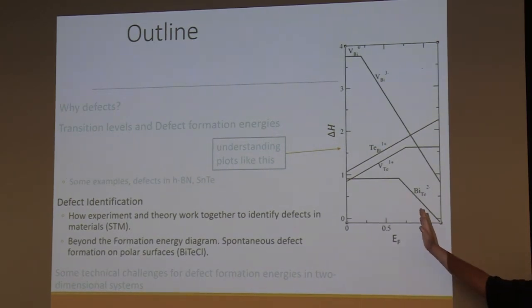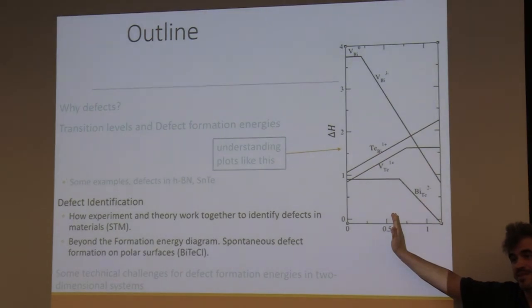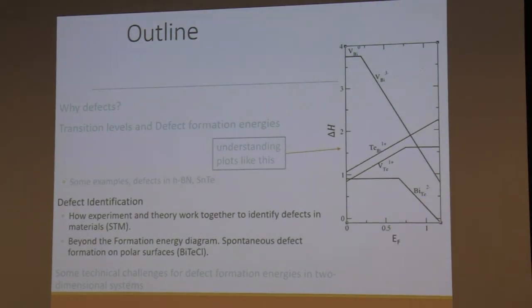So if we assume the Fermi energy is up here, then that means we make a lot of acceptors, which lowers the Fermi energy. All right? So the most probable place I would say would be somewhere kind of where this donor, yeah, somewhere in here. So it'll be essentially mid-gap. So we wouldn't expect this to have a lot of free carriers, either holes or electrons.